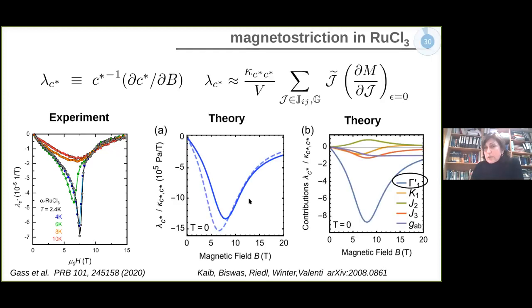So we can now calculate that. So this would be the theoretical way of calculating magnetostriction, where we have now these magnetoelastic couplings, and the derivatives of the magnetization with respect to the couplings, we can also numerically estimate them. And this is what theory gives us, so what these models that I was showing to you are able to describe, in fact, this very strong response of the lattice due to the magnetoelastic coupling to the magnetic field.